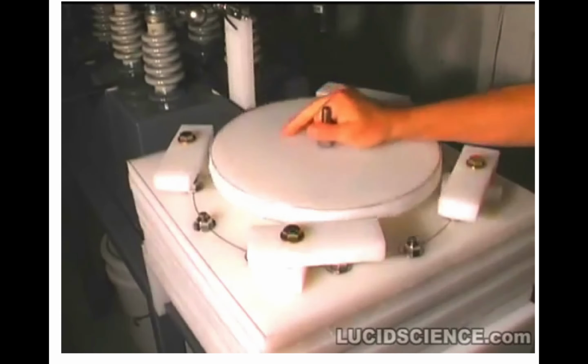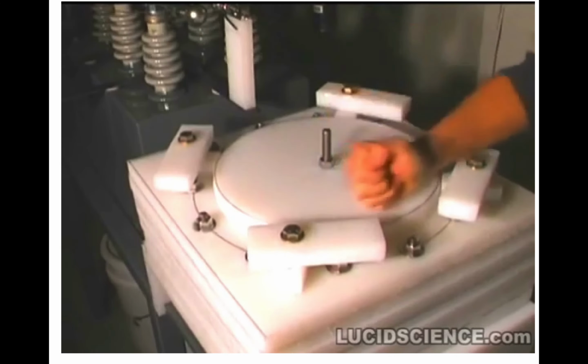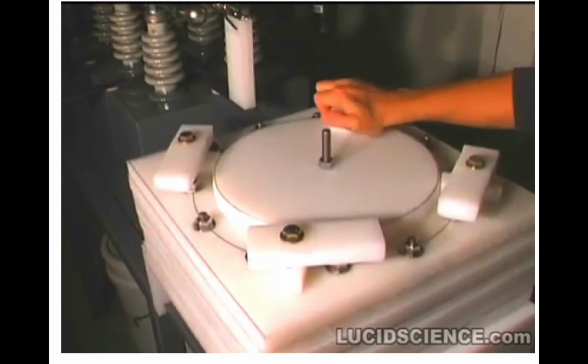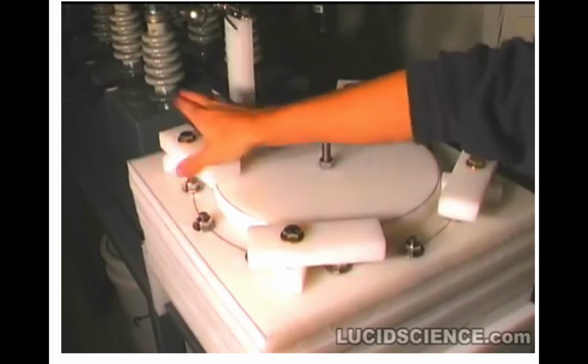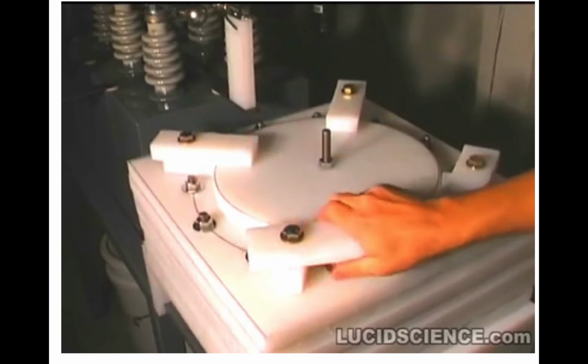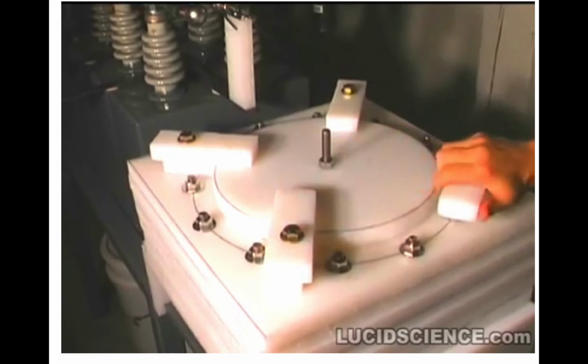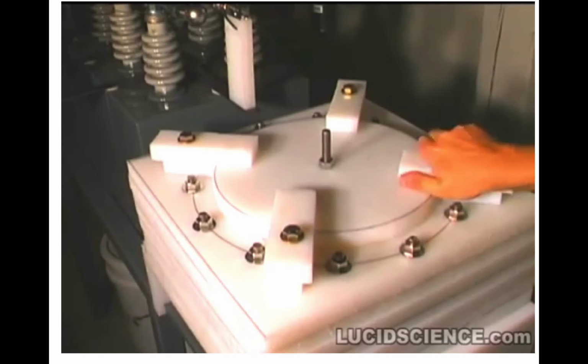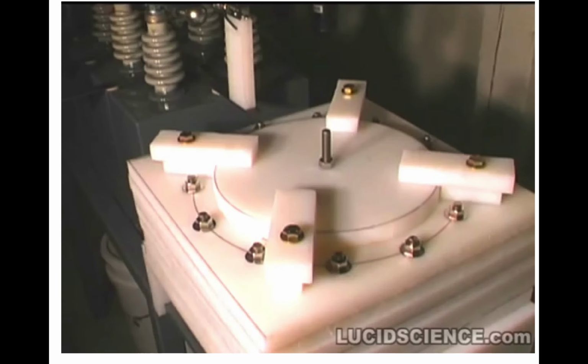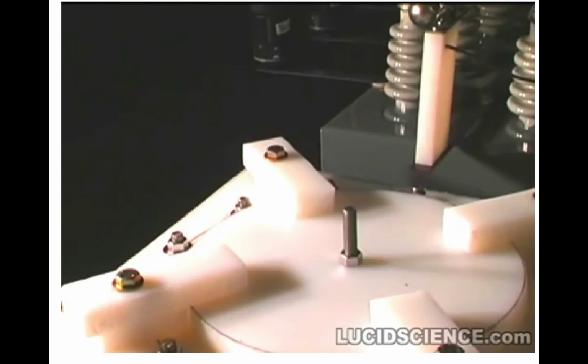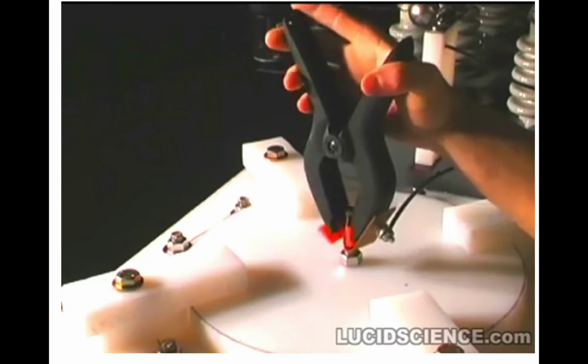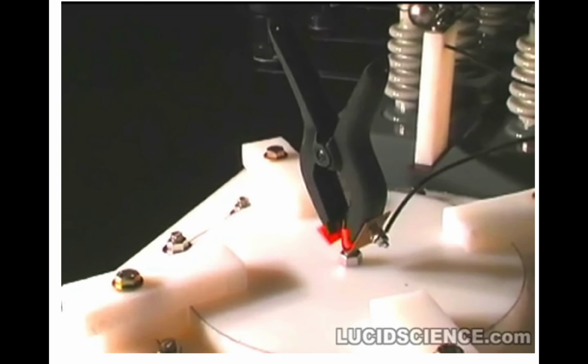The purpose of the rock disaggregator is to separate mineral samples at the boundaries without fracturing the grains. Mechanical crushing systems usually fracture small grains or gems, but this system separates them without damage. The charging output is set on low for 5-second pulses.